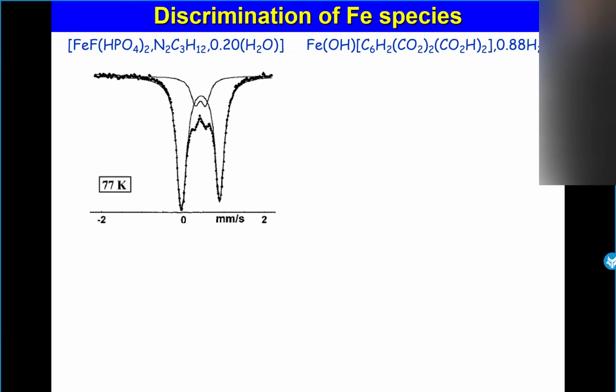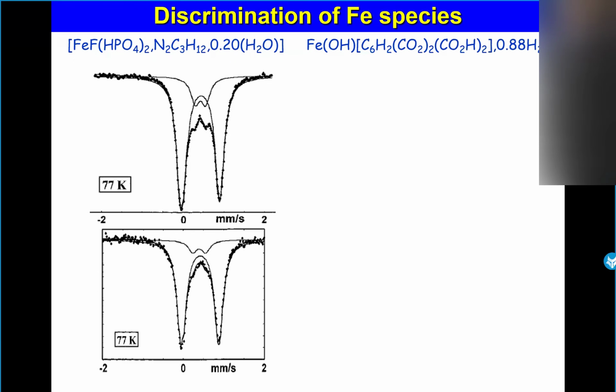Okay. So what I had done, I used again the cryofurnace. So we increased the temperature and we repeated the spectrum inside the cryofurnace in situ to get the new spectrum. And you can see a decrease of the doublet. So that means that, of course, there were water molecules. And after we put the powder out of the cryofurnace during one night, on the day after, we made a spectrum and we recovered the first spectrum. That means the system was able to breathe, to take water, to expel water, to take again.